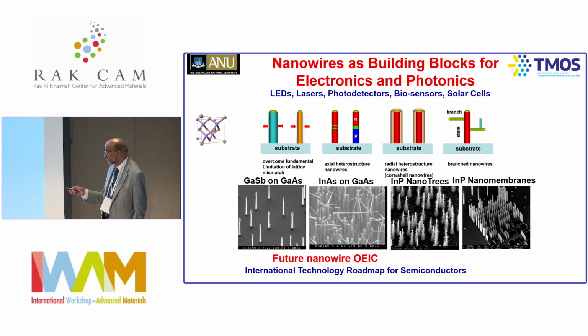But in this case, if we make materials with a larger lattice constant or a smaller lattice constant, they can expand or contract without creating any dislocations. That means, in principle, you should be able to make nanowires of any material on any substrate without the constraints of lattice mismatch. You can also make axial heterostructures. These green materials are different than the red materials. Also, you can make p-n junctions by doping different parts of the nanowire for making lasers and LEDs and solar cells also, which I will come back to.